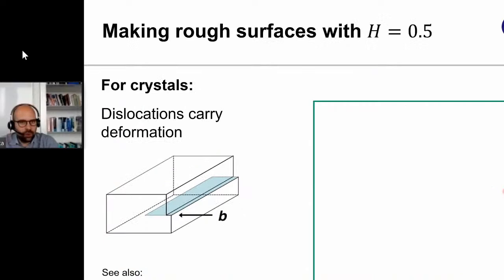Okay, so what's going on here? Why do we get self-affine scaling? And it's actually very simple to explain for a crystal in which the dislocations move uncorrelated. So if we have a dislocation as the carrier of plastic deformation in a crystalline material, then when that hits the surface, it will leave behind a step on that surface, a step with a height that's correlated to the Burgers vector of that dislocation.